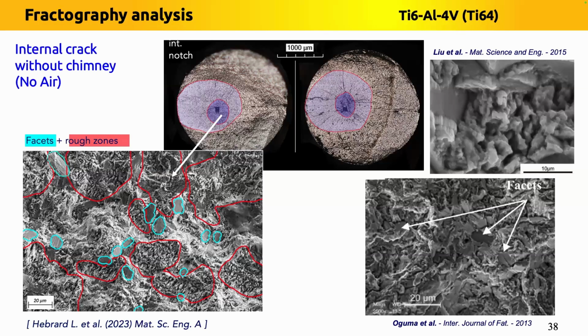So first, if we look at the specimen without a chimney, we can classically observe in the black area here a rough surface and small facets. This is in agreement with literature observations. You can see the facets here by different workers.